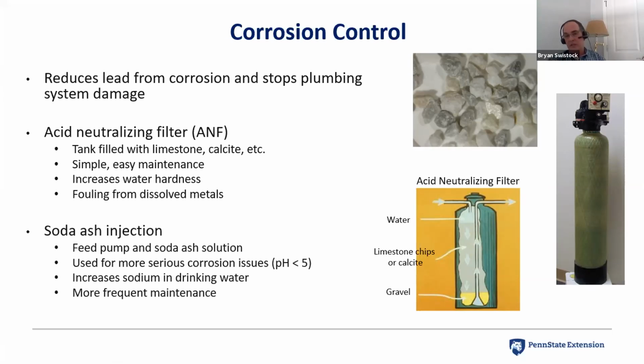In severe cases, we can use things like soda ash injection, where we'll take a feed pump and inject a slurry of soda ash directly into the water line. More maintenance here, a little bit more tricky, a little bit of hazardous material. Got to be careful with soda ash. But where we have really corrosive water and an acid neutralizing filter just can't raise the pH enough and can't get that corrosivity index up high enough, we can use soda ash instead. We increase sodium in this case instead of hardness, which is a concern for some people. And there's definitely more maintenance. These are a little bit more tricky to deal with, and they're not preferable for sure.